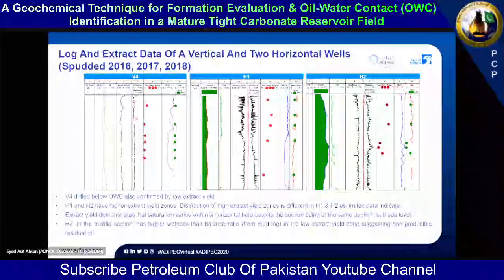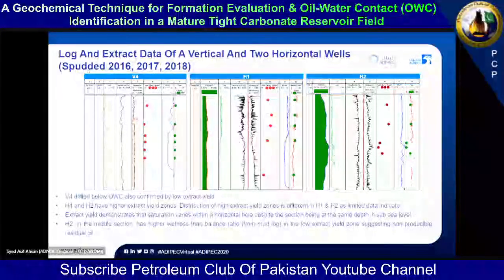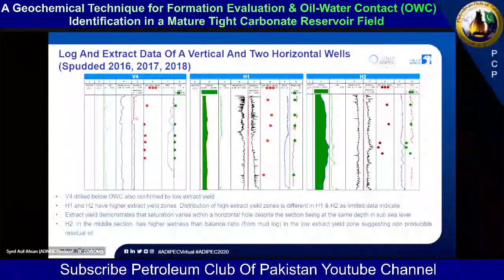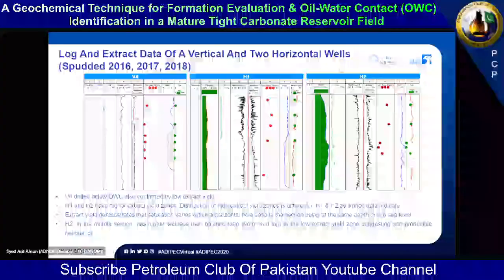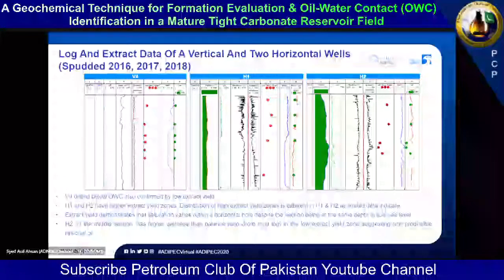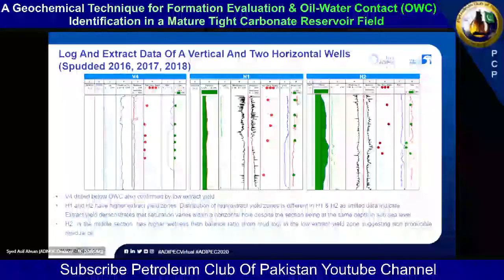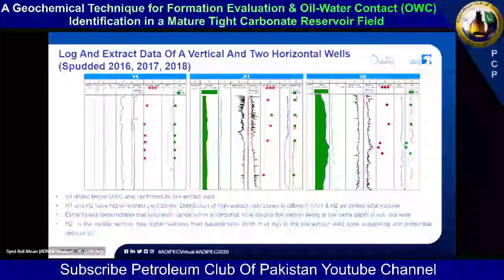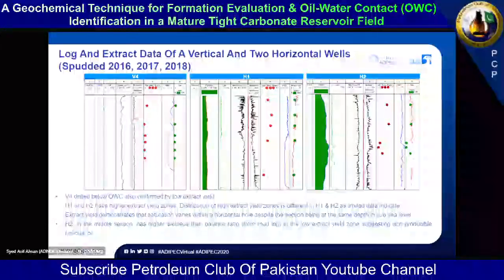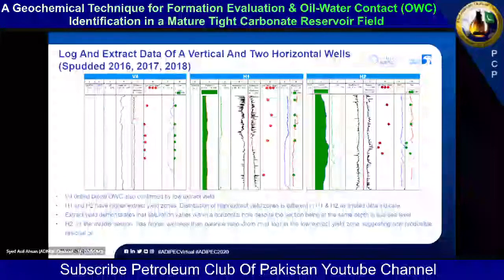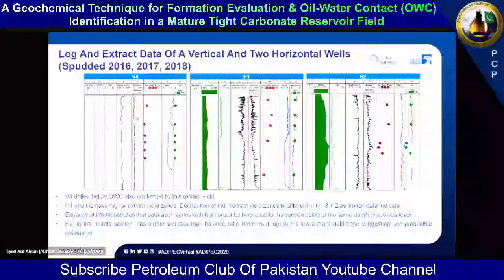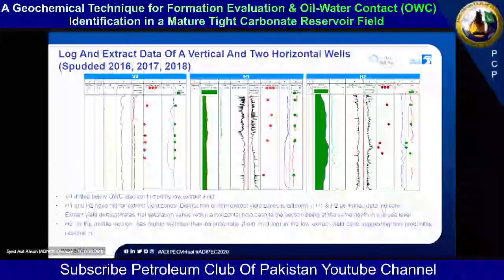Now, in the horizontal hole, we had only well cuttings. So well cuttings are also not wasted. They are also good samples to have a look at. And these broken lines in the horizontal well, the red line in the last track, is representing the resistivity-based water saturation. And you can see these core-derived extract yield are nicely matching with the petrophysically-derived water saturation.